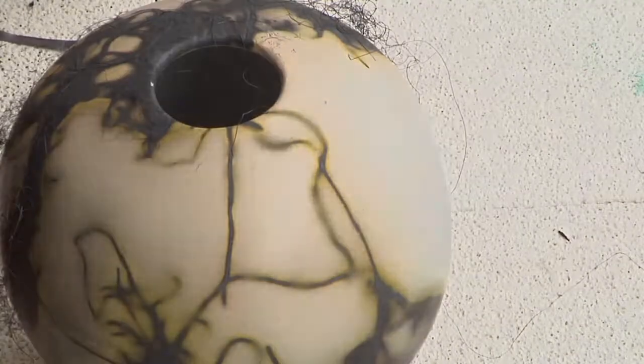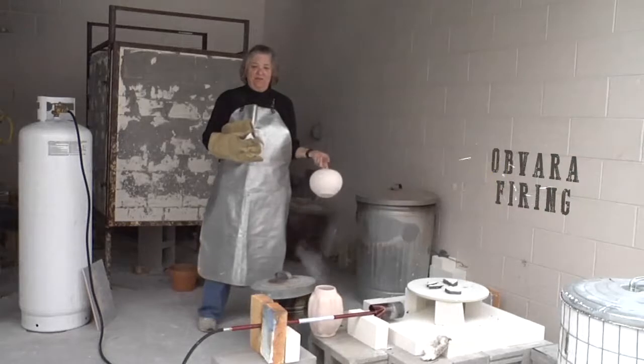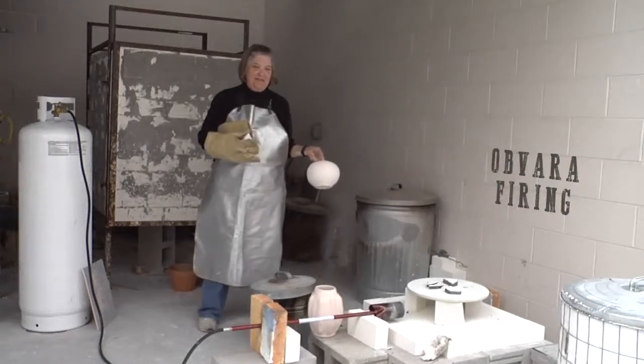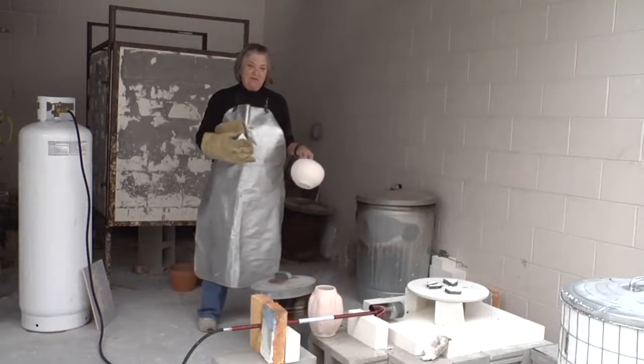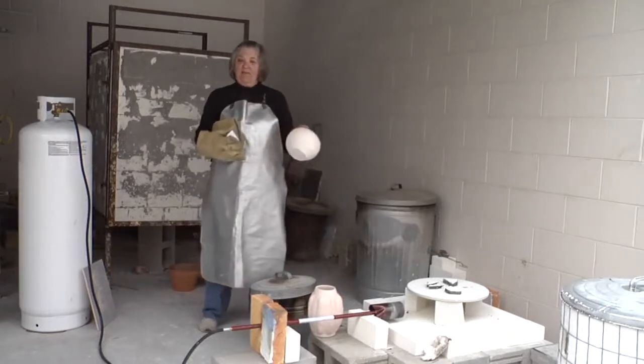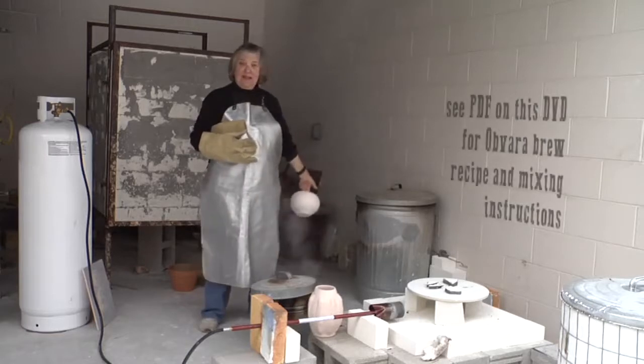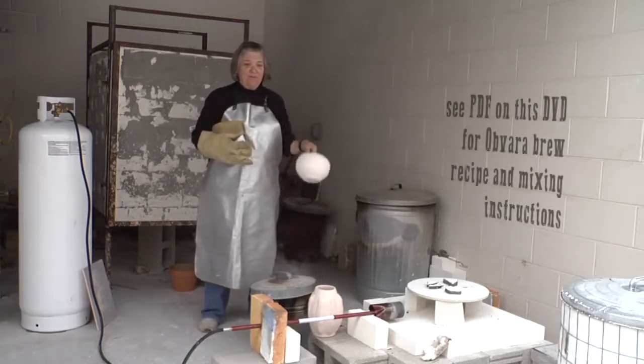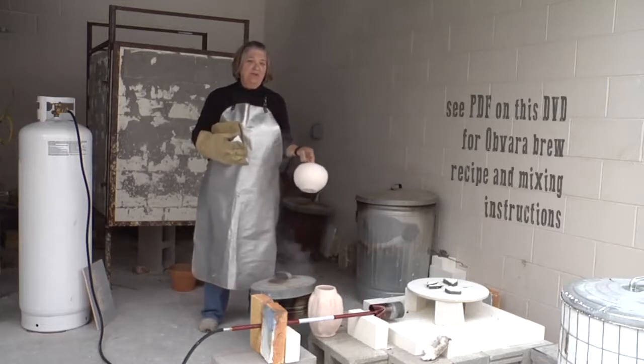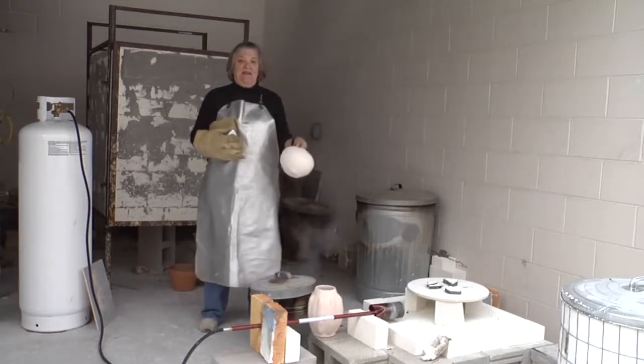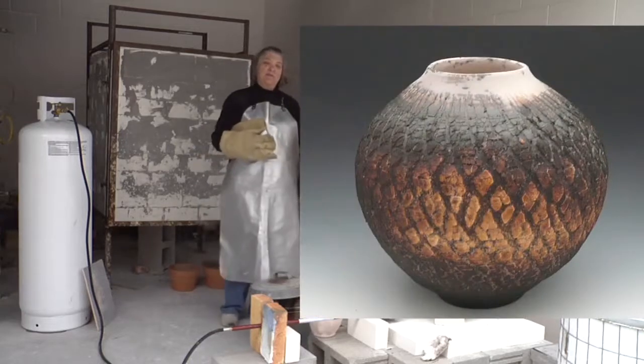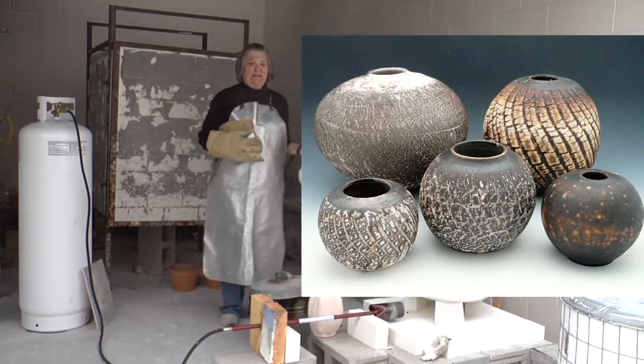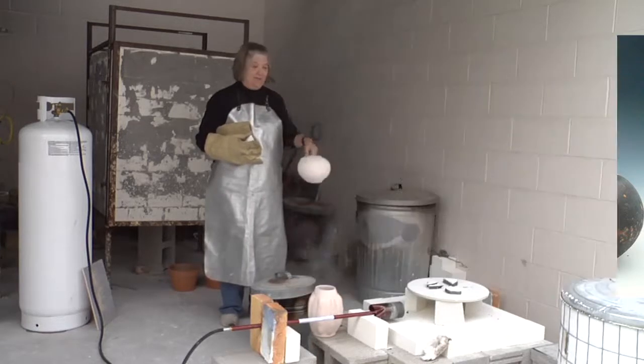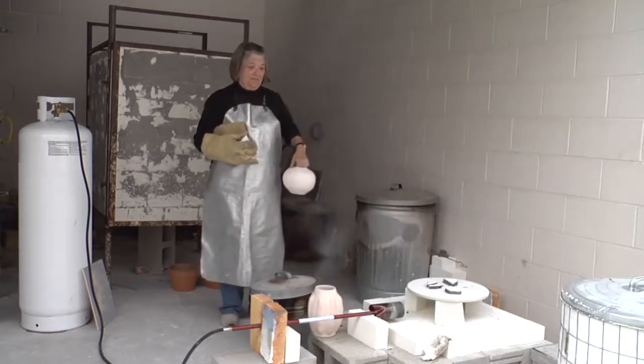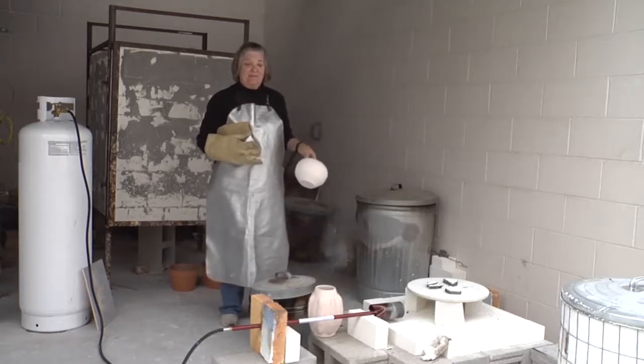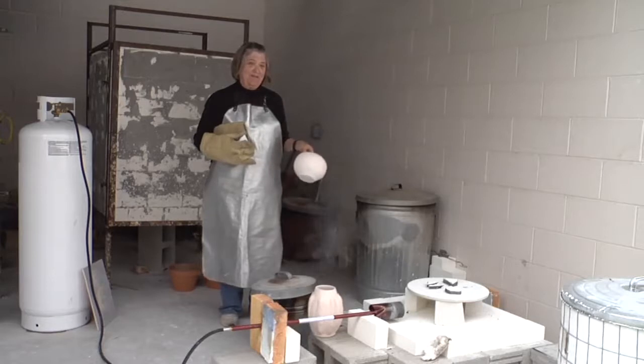So good firing. Okay, I'm going to do one more use of a raku kiln, and this is an Obvara firing. So this goes up to 1650 degrees, and when the piece comes out, rather than smoking it in a can with a combustible, it's going to be dipped in a solution of flour, yeast, sugar and water. And it has some amazing results. Supposedly this is an Eastern European technique or possibly Siberian, and it was originally used to seal the clay. So it's becoming pretty popular just because the effects are so beautiful.